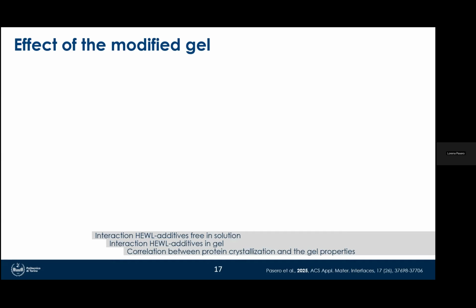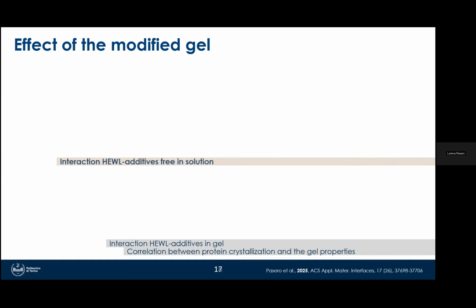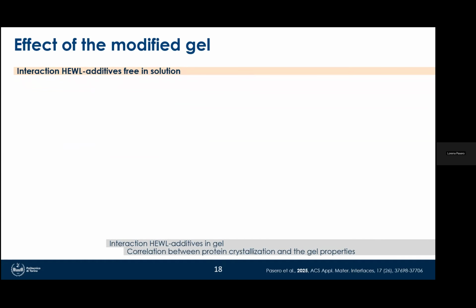Then we wanted to better investigate which was the effect of the modification of the gel, and so the reason, the mechanism behind it. So we started by understanding the protein additive interaction in solution. And to do that, we performed a microbatch crystallization where we varied the protein to additive mass ratio.